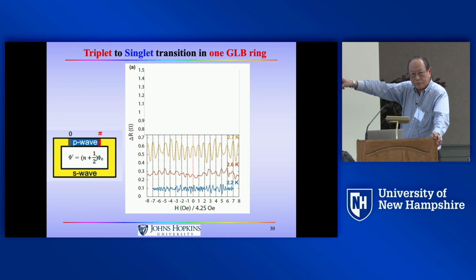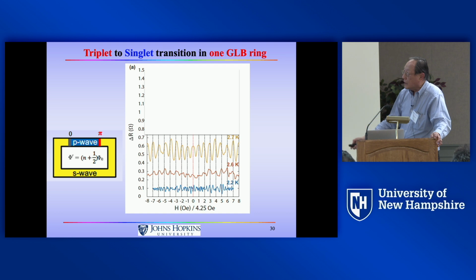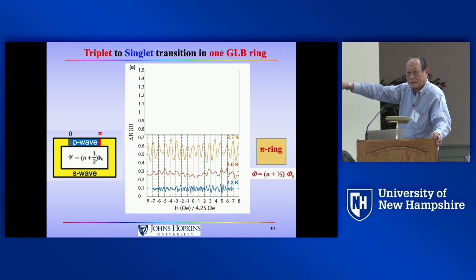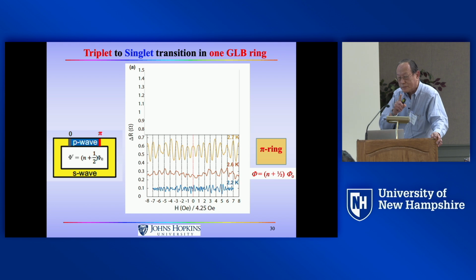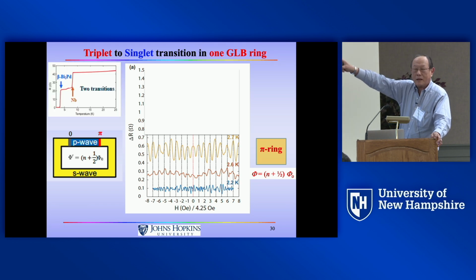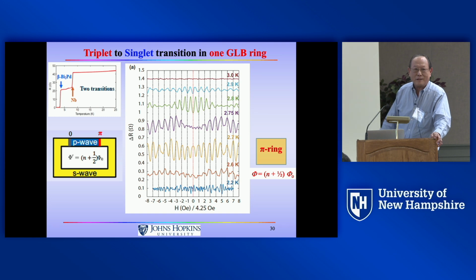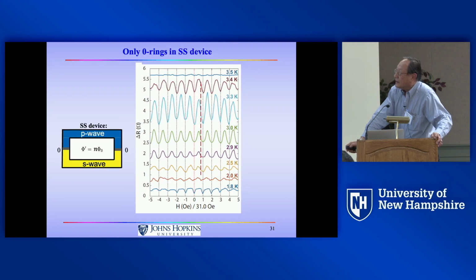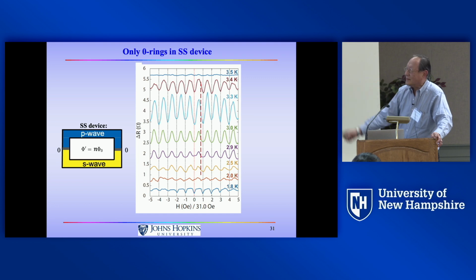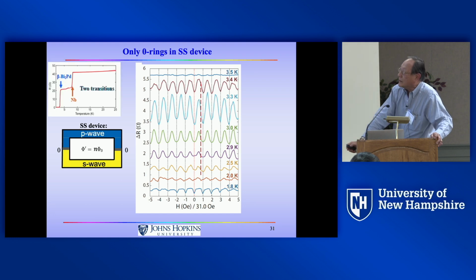Since this thing has 2 superconductors, what I show you is at the TC of the triplet. If you now measure, it's half flux. If you go slightly higher temperature, the bismuth palladium already goes normal, but it becomes a superconductor because of the proximity effect. What proximity effect? Due to niobium. Niobium is slightly higher. It will form what? Integer. So in the same ring, you can see half integer at low temperature, integer at high temperature. Okay. So if you make the other one, you will see nothing except integer. Nothing. Always integer. Right?